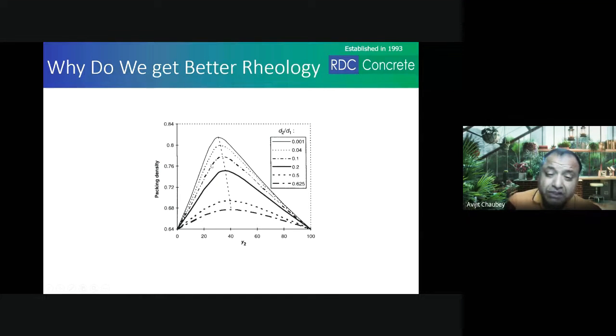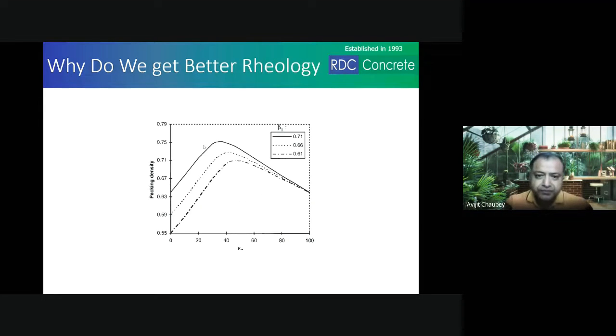With 20 and just 2.36 aggregates, mixing of that gave an even higher particle packing, and so on. So this is basically the theory that gap grading materials give you much better particle packing, and that is because of the myth. The myth is not true, that the void sizes between the aggregates are half that size. It is much less than half the size of these aggregates.